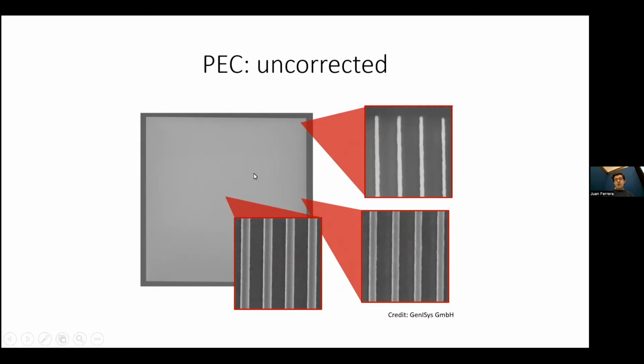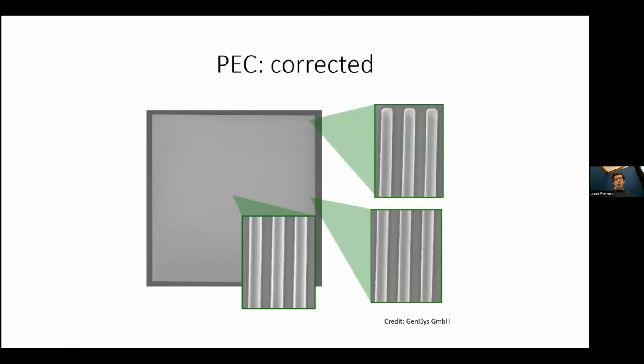Whereas if you run it through the proximity effect correction program before, you can see that all 3 instances that we're showing here are pretty much the same. So you'll get very good fidelity if you use a proximity effect correction program on all your patterns before you expose them. You will pretty much always get what you want. And if you choose your doses carefully, you might not even have to do a dose matrix. So now I'm going to hand over to Mark to continue the presentation.